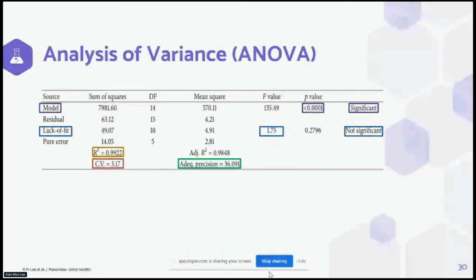So what we can see here from the ANOVA is that the model is significant because the model has a highly significant p-value. The lack of fit is only 1.75, meaning the lack of fit is not significant. The low coefficient of variation and high R-square values indicate high precision and good reliability of the experimental values. And lastly, the adequate precision measures the signal to noise ratio, where a ratio greater than 4 is desirable.